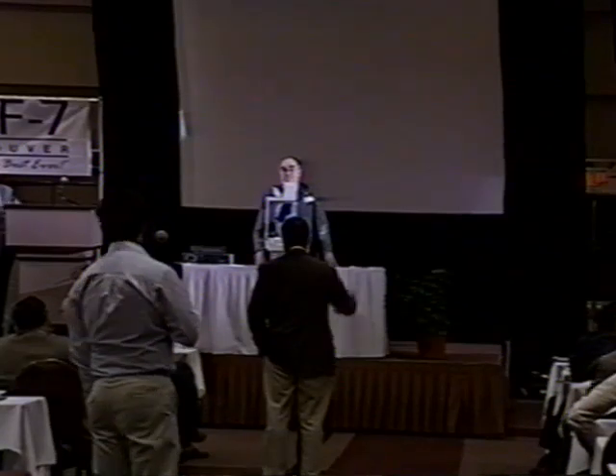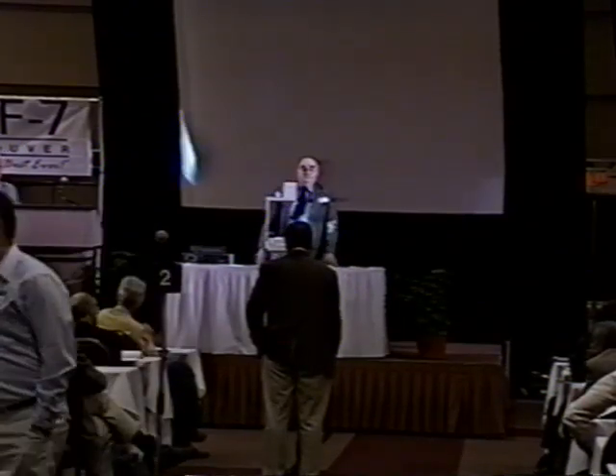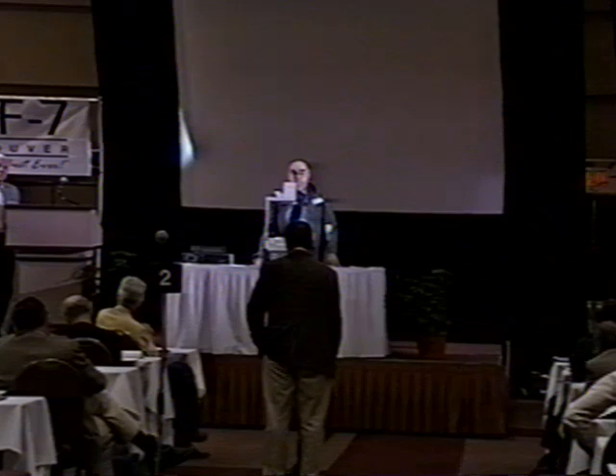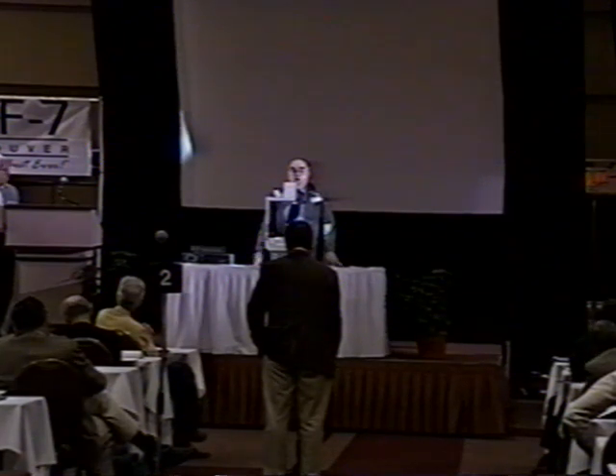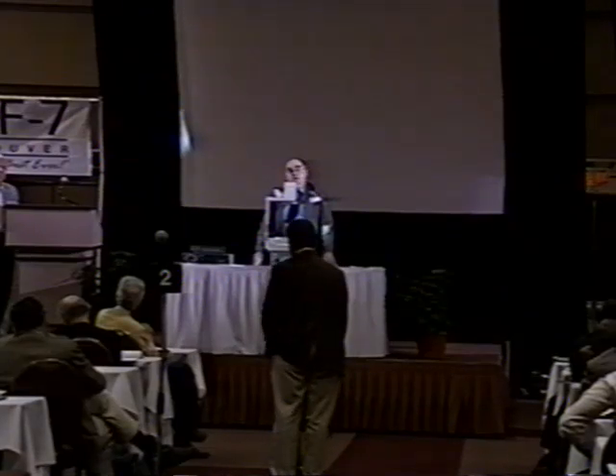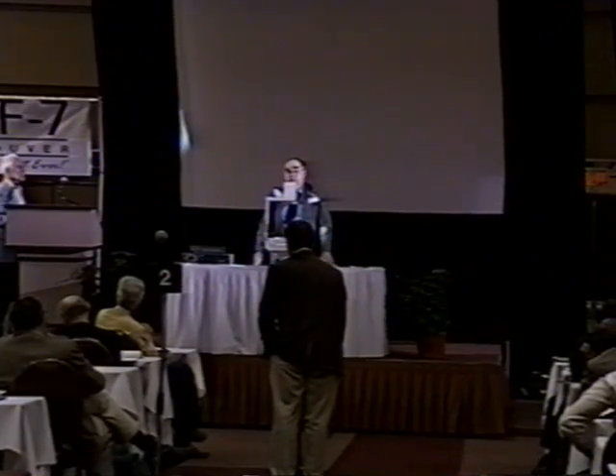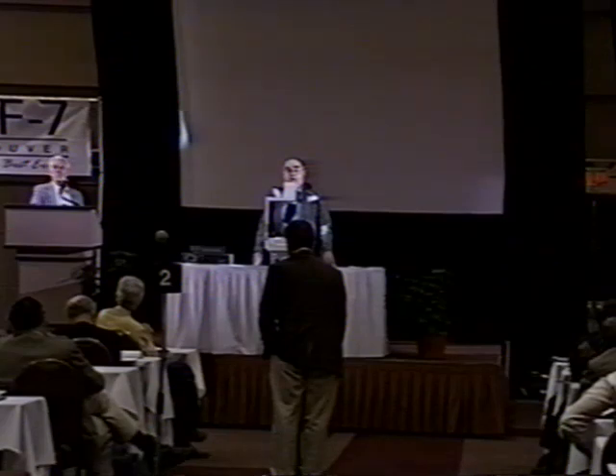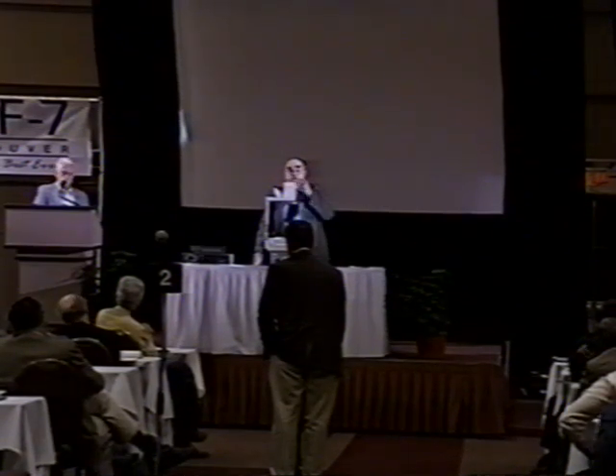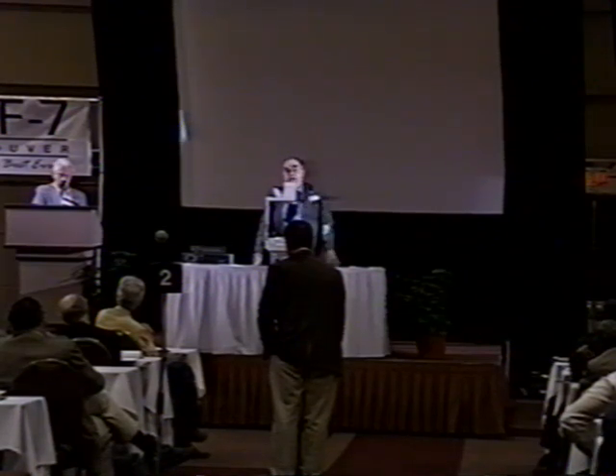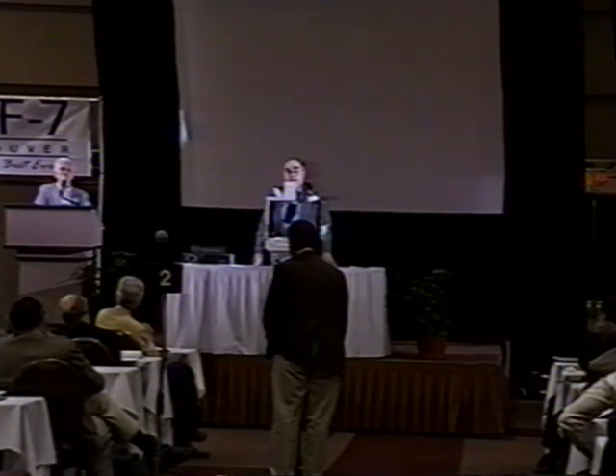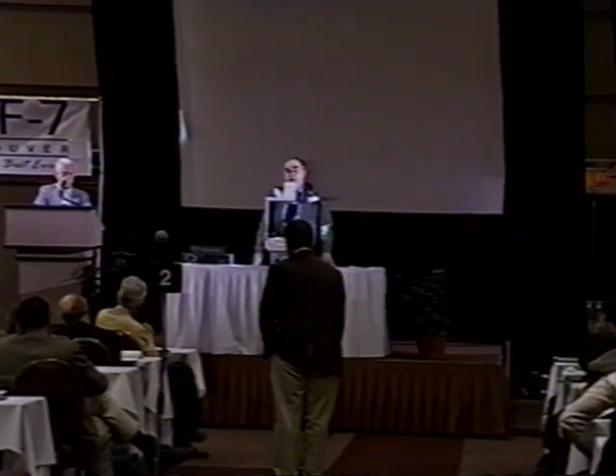Okay, thanks. Scott, what was the excess power that you would typically get out of it? Well, I calculated about 5 to 10 watts. It was approximately 10% of power input, but it wasn't very well insulated. I didn't use a door or anything of the sort. If I used much better insulation, I could estimate easily, even on this scale, that I'd be doing at least 50% excess power. And then I did try to optimize the power output.